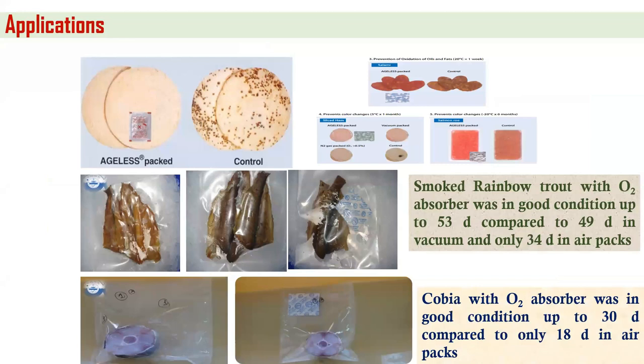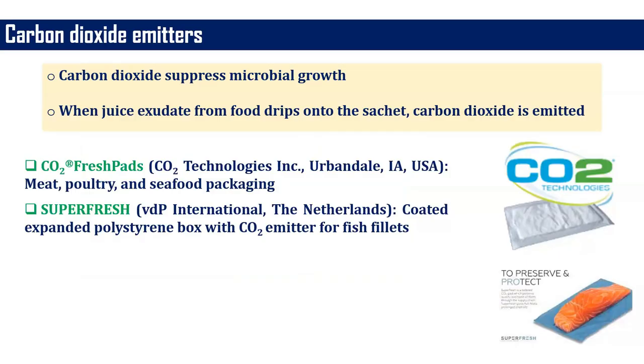Coming to the applications, it has wide applications in the case of food. In our lab, we have used it for extending the shelf life of different fishes, like rainbow trout. It is a cold water fish. When we packed the rainbow trout with oxygen absorber, it was in good condition up to 53 days compared to only 49 days in vacuum packing and only 34 days in air packing. So there was a clear shelf life extension when we used oxygen absorber. Another fish, cobia, was also packed with oxygen absorber and it was in good condition up to 30 days compared to only 18 days in air packs.